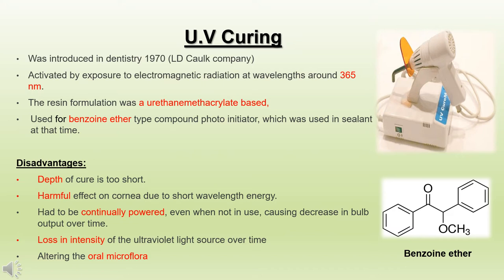The first dental curing unit was developed in the 1970s. It was the Nuva light that used ultraviolet light in order to cure the material. The first photocuring units were designed to emit ultraviolet light about 365 nanometers through a quartz rod from a high-pressure mercury source. This development was seen as a revolutionary step in dentistry. However, this was discontinued because of the drawbacks of ultraviolet light used in the system. Furthermore, these lights were not very effective due to the shorter wavelengths that limited the depth of the cure.